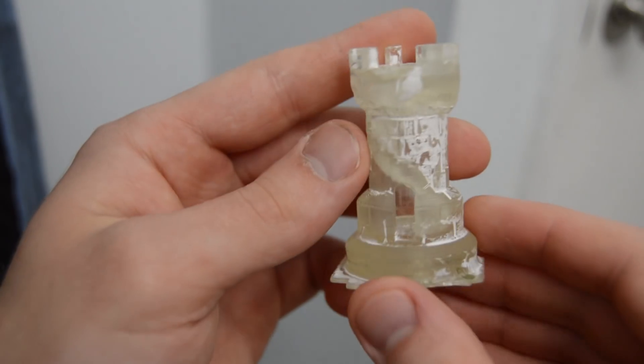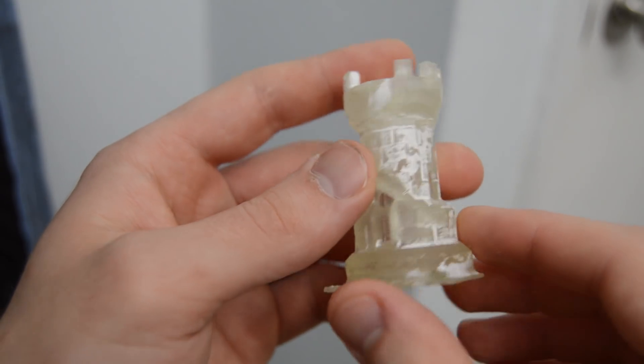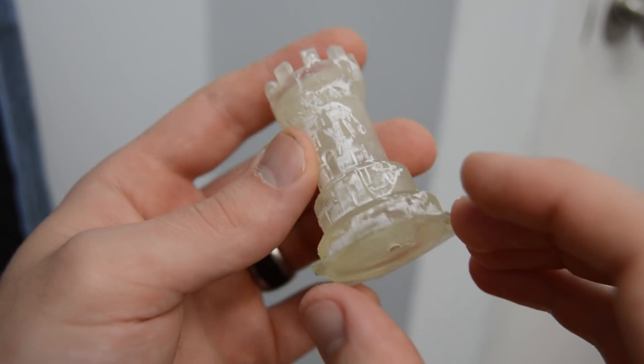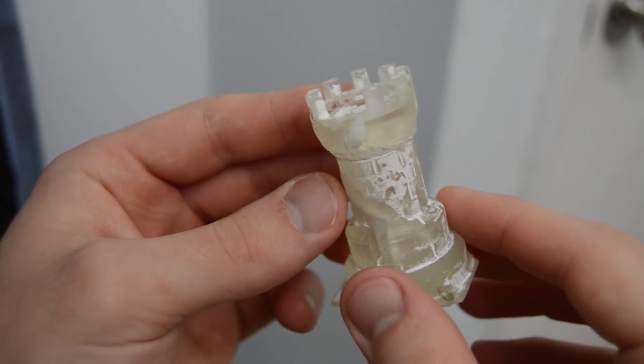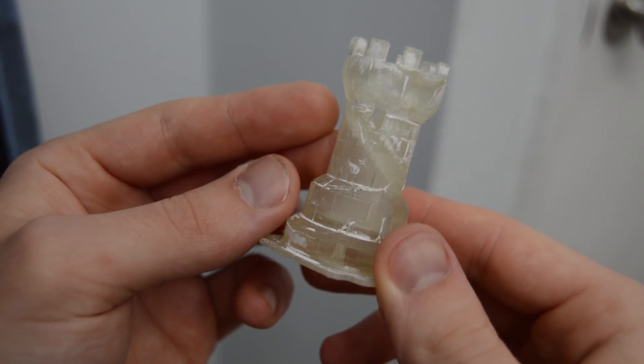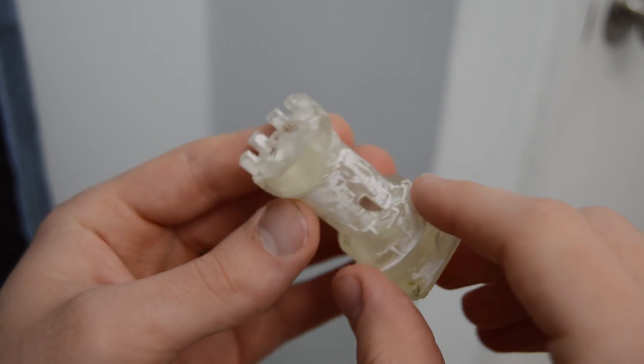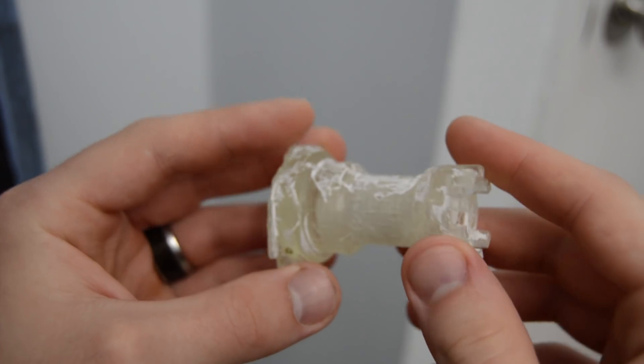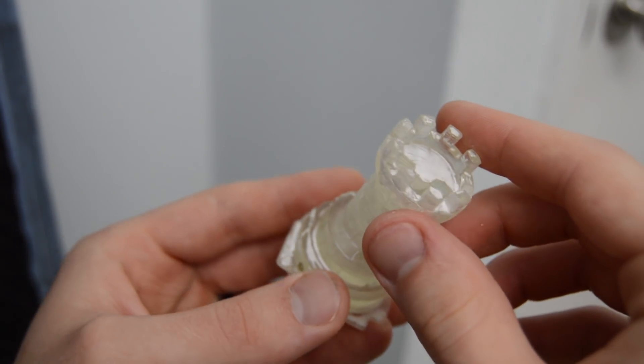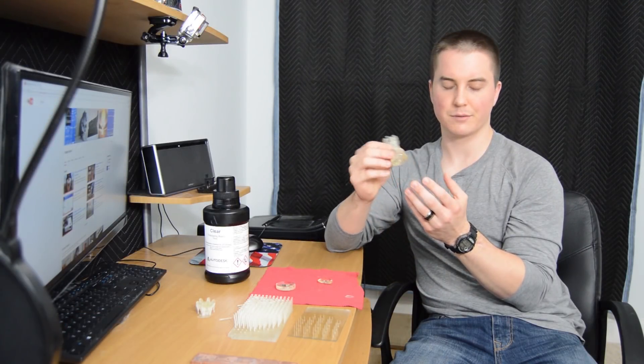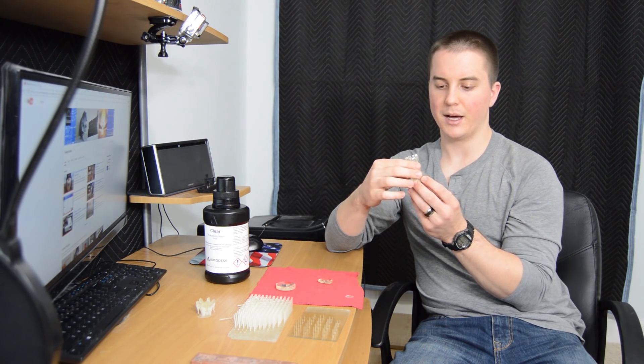What I did was I dipped this in the polycrylic and it came out looking pretty clear. I wanted to just see how that polycrylic finish would hold up to solvent. I did soak it in IPA for a few hours, took it out, and it was very cloudy. The surface had gummed up and most of it wiped off, so it was fairly well ruined.